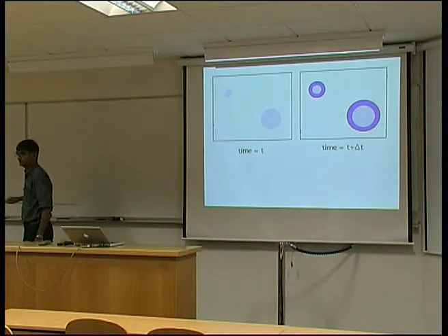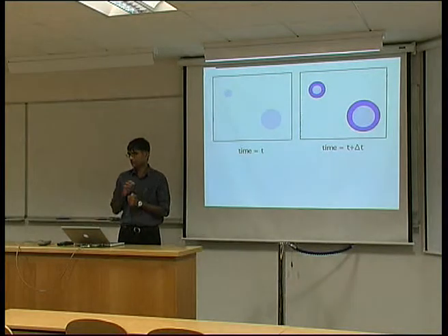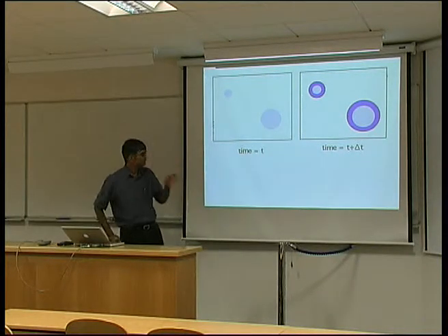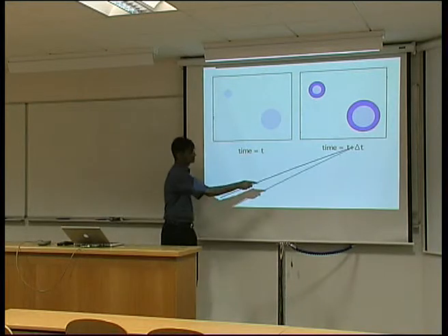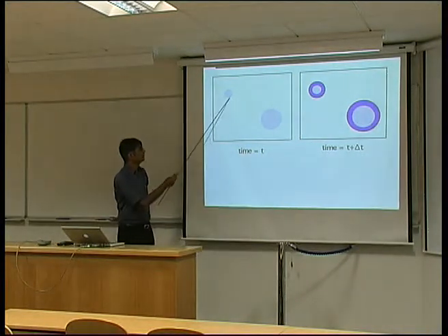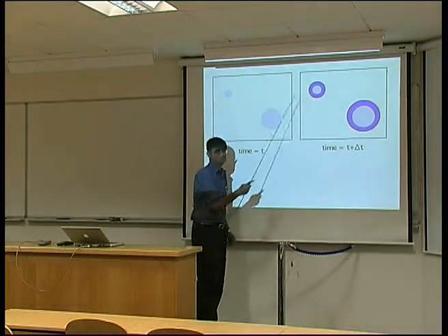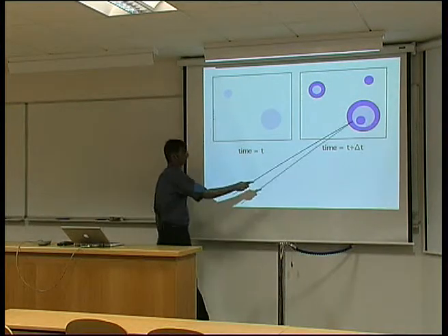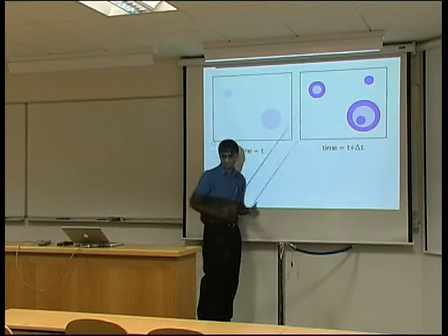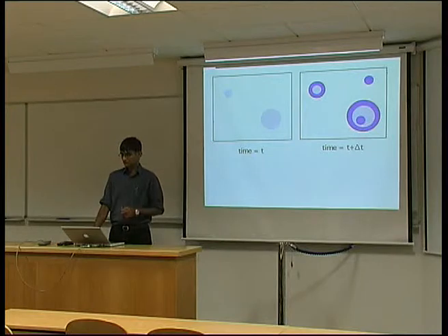So I'm going to continue with overall transformation rate theory. And just to summarize what we did in the last lecture, we derived the Avrami equation by considering the evolution of particles following a short time period delta t. So supposing we start with two particles at a time t, and those two particles have grown by a certain amount, and we may have nucleated two more particles, then clearly this is wrong in the sense that we can't transform in a region which has already transformed.